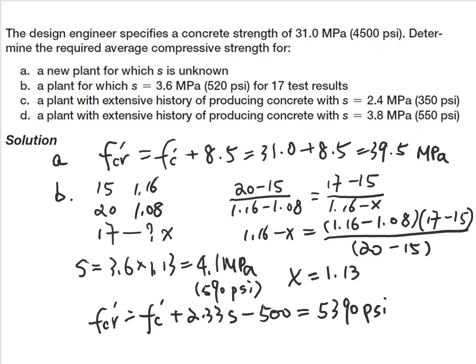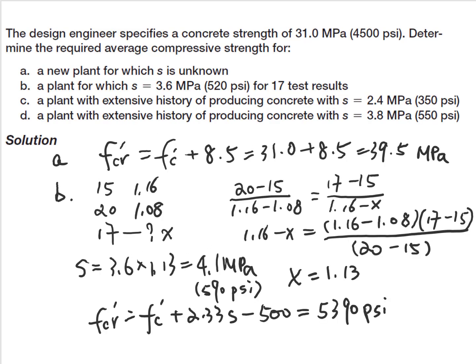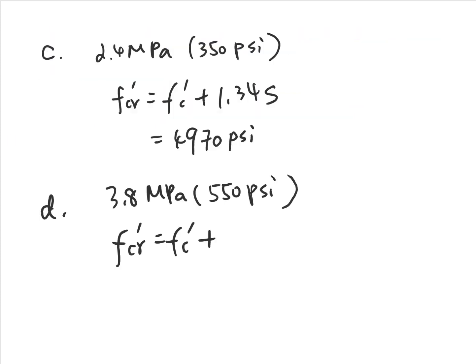So f'cr equal to f'c plus 2.33S minus 500. So this will be equal to, if you calculate it, 5390 psi.